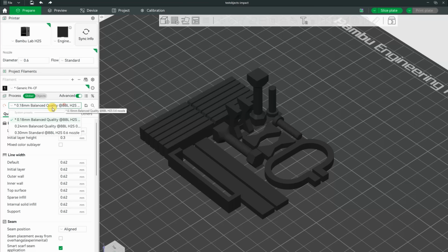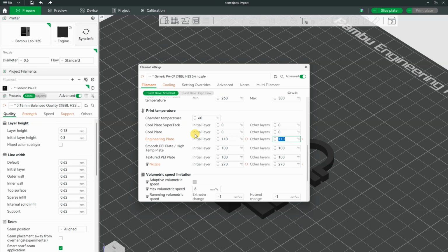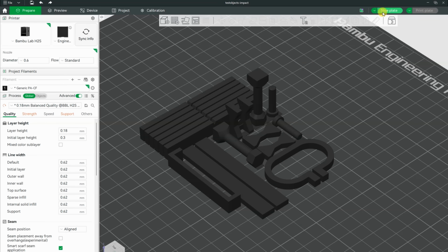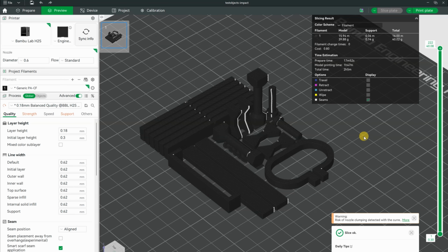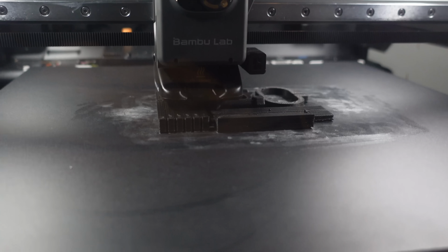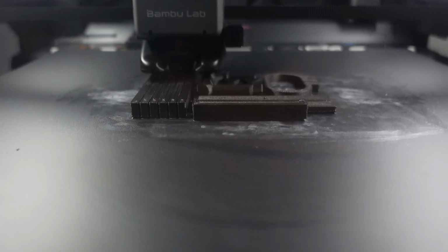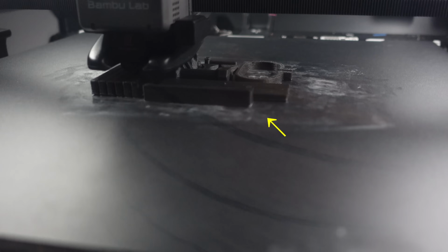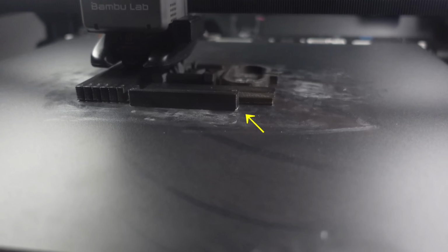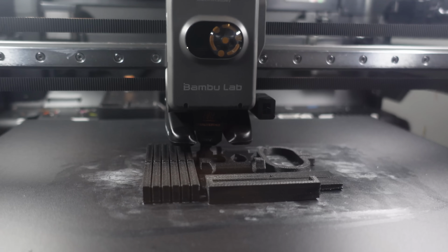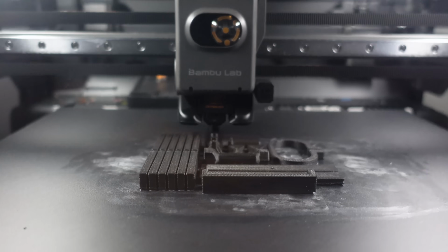Another 8 hours of drying on 85 degrees Celsius, and I am reducing the layer height to 0.18mm, still with 0.6mm nozzle, and also I increased the bed temperature from 100 to 110 degrees Celsius. Of course now the print time is longer. The printing is much better and it will be finished in approximately 15 minutes, but I can still see some warping on few test objects.